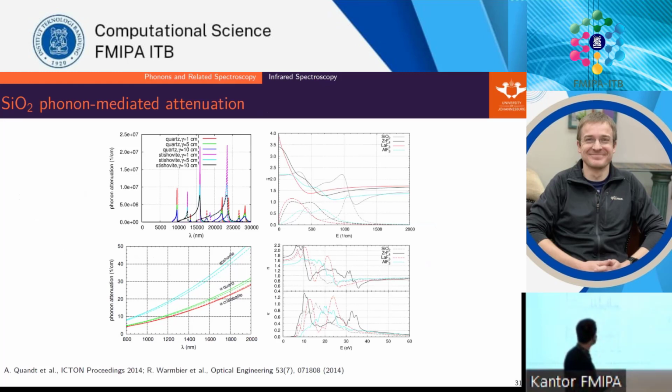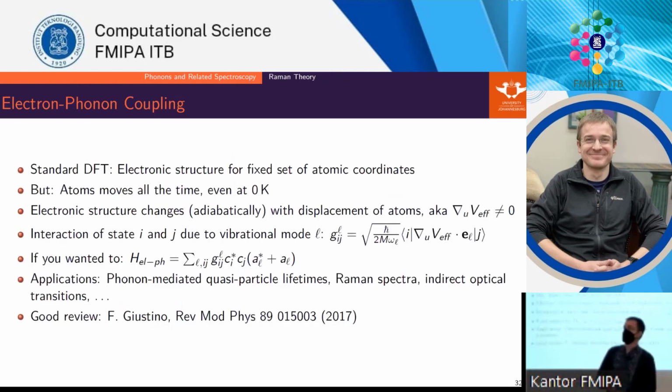So here is a bit tricky to see online, I'm afraid. I have some silicon dioxide and a few other materials, some lanthanide and some other materials which you can find in glasses, for example, right? These are not glass unit cells, but these are materials you use in glasses. And now basically, if you take the spectrum of your glass sample, your waveguide, for example, at different positions, you measure the infrared spectrum, and you then can see, okay, this peak here belongs to silicon dioxide. This peak here belongs to aluminum fluoride, right? And then you can see, okay, is this a homogeneous sample? Do I have the right ratios of everything in there? So this is a very cheap and quick thing to do experimentally and numerically, which is the perfect thing to have.